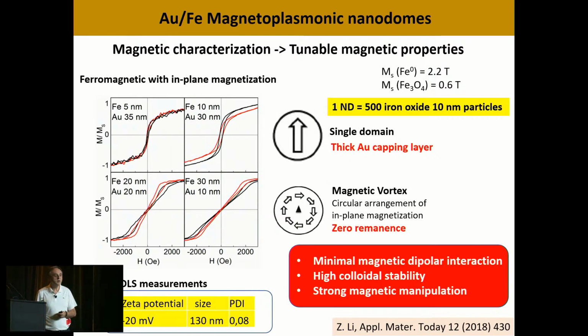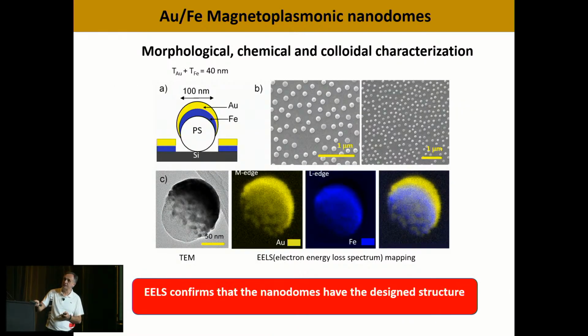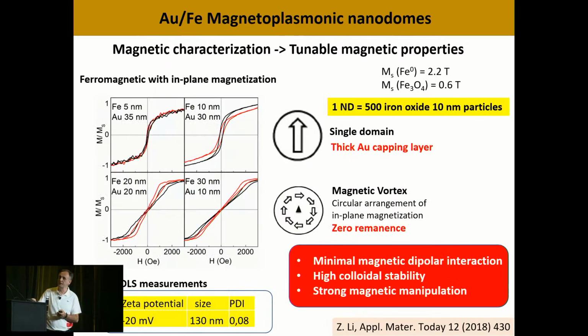So then we went on and measured the magnetic properties. What we did is keep the total thickness of these two layers constant at 40 nanometers, and then we changed the ratio. We went from 5 nanometers of iron, 35 nanometers of gold, 10 nanometers of iron, 30 of gold, and so on. When we measure the magnetic properties, we see that when the iron is very thin, we have hysteresis loops similar to the ferromagnetic nanoparticles I showed you in the beginning. So they have a remanence, they have some moment at zero field, meaning that these nanoparticles could interact with each other and potentially agglomerate.